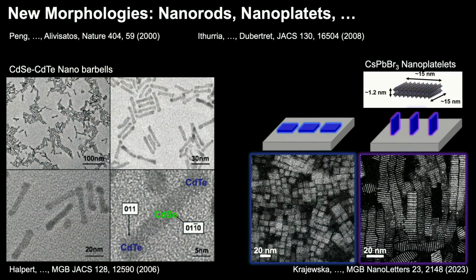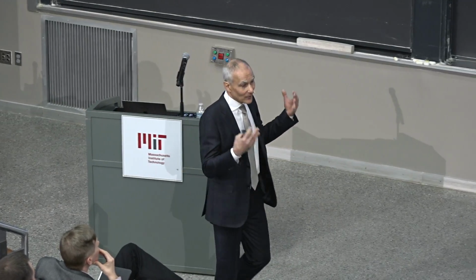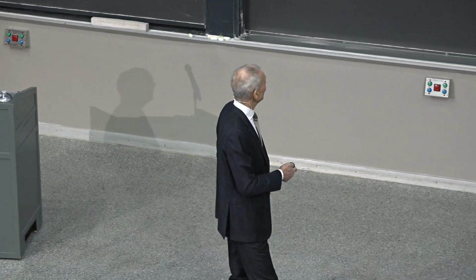The ligands that we used to make the dots, we used one kind of ligand, the phosphine oxides. But if you mix and match and use multiple different kinds of ligands that have different interactions with the different crystal faces, people realized in the early 2000s, about 7 years after the synthesis, that you could start to grow different shapes. So Paul Alivisatos and his group made rods, Dubertret in France made platelets. These are our contributions. These are cadmium selenide rods with little bells of cadmium telluride, where the electron goes; you create it in here and then it goes to the edges. These are nanoplates of cesium lead halide perovskites, very, very thin, made recently in my group, for instance. So not only do we have different materials, we also have different shapes, and now the universe that's available to us to mix and match becomes really infinite. And that's a little scary, but if you're clever, then you can figure out how to mix and match things to try to make new materials.